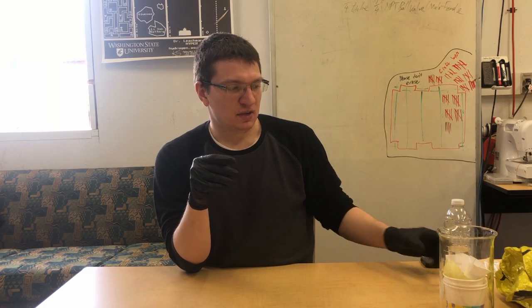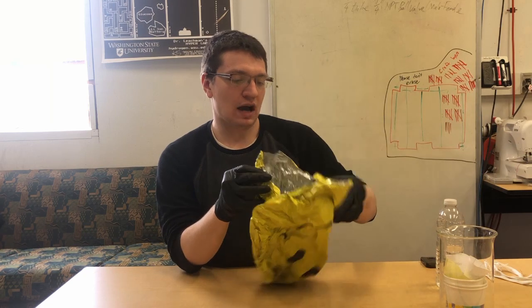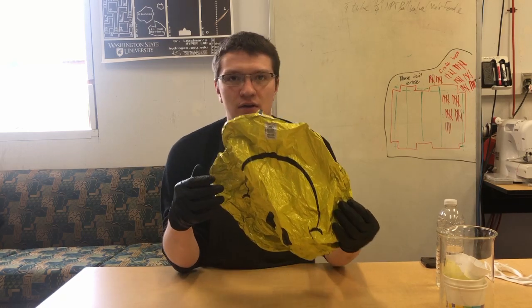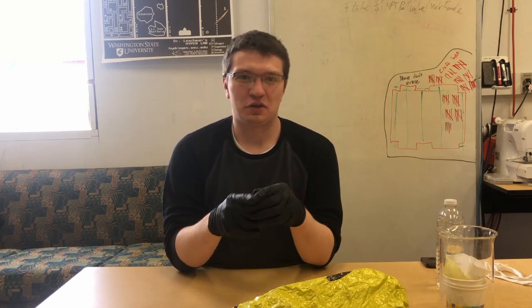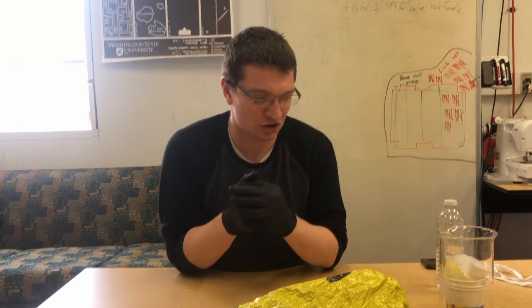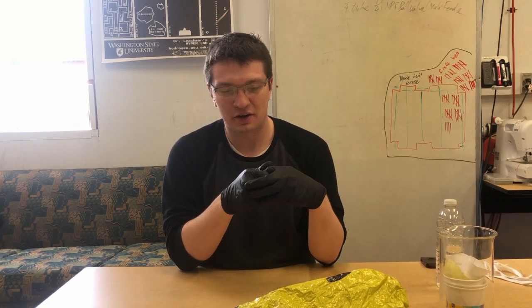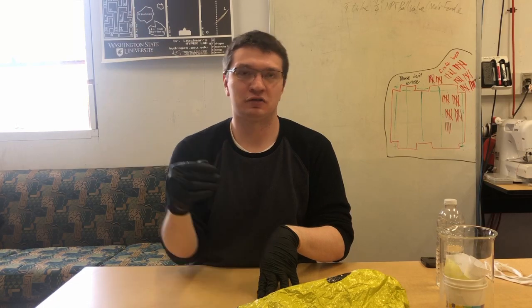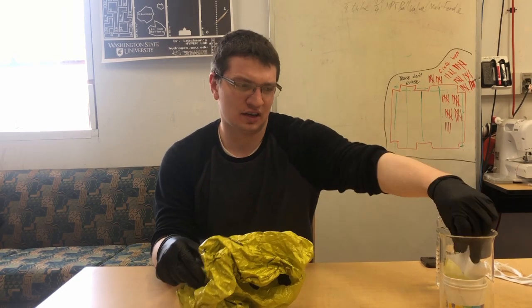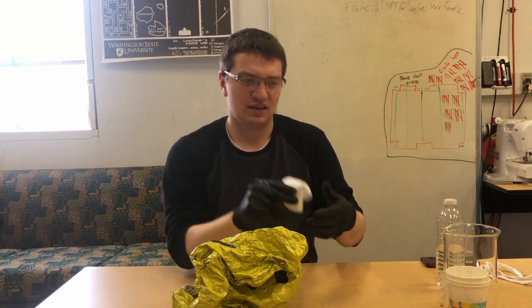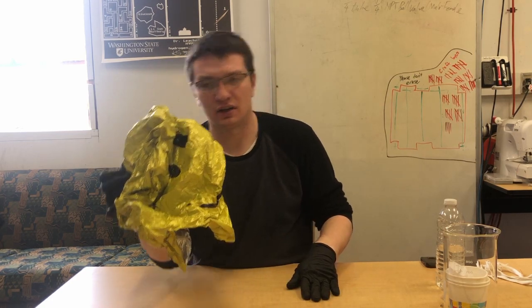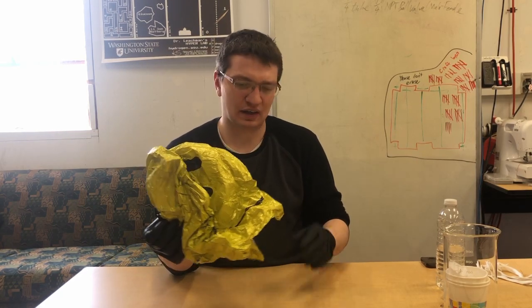So the main question then becomes, how are you going to deal with the fact that plastics have extremely reduced ductility when you get cold? The typical cliche of someone throwing LN2 on a lock and then taking a hammer to break it is not terribly far from the truth. You can basically freeze an apple with LN2, drop it on the floor and it will shatter. And the same holds true for plastics. When you're crumpling a bag like this, you're actually introducing a lot of elemental folds like a vertex that have extremely high stress concentrations, so much so that you could just tear your bag apart when trying to crumple it. And so the question becomes, how do you manage that crumpling?